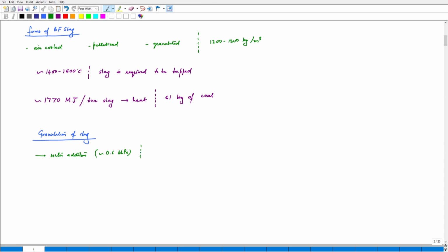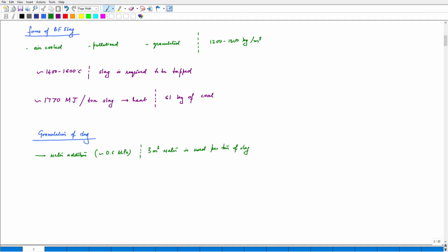Now what else? 3 meter cube water is used per ton of slag. So it doesn't appear to be a very large quantity, but what happens is water pickup by the slag during this process is observed. So granulated slag, when you are adding water with pressure, it picks up water with it, and then we see the presence of water in the finished product. So this is what I am saying, nearly 30% water is observed in the slag. When we are cooling it down by the granulation process and when we are adding water with pressure, this is going to happen.